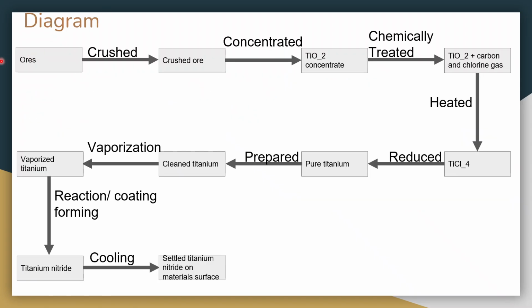Here is a diagram of the process of taking titanium ore into titanium nitride. You start with your ore that is mined using the three mining methods previously mentioned, then it is taken into a crusher that crushes the ore, then it's concentrated into TiO2, which is then chemically treated with carbon and chlorine gas, heated to form titanium tetrachloride, which is reduced to make pure titanium, and then preparing, which is basically cleaning the titanium, vaporization, which is your vaporized titanium, and then reaction and coating formation, which forms your titanium nitride, which cools into your settled titanium nitride, your finished product on the material surface.